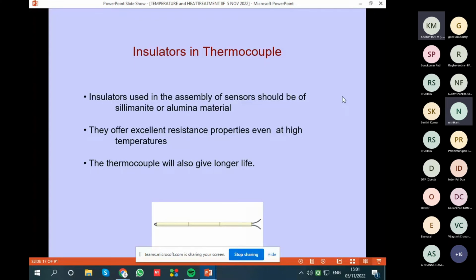So another interesting aspect, there are insulators in the thermocouple. These are not porcelain insulators. These are insulators which will protect the thermocouple wires even at a high temperature. These are recrystallized alumina or alumina insulators. They have a property that they are electrically insulated even at high temperatures up to 1600 degrees centigrade. If you use porcelain insulators, they become short electrically at high temperatures, and if they start conducting, then the millivolts generated by the thermocouple will be wrong. So ensure that the insulators are always of that quality, recrystallized alumina or alumina.